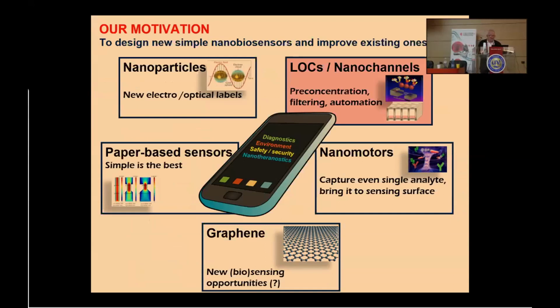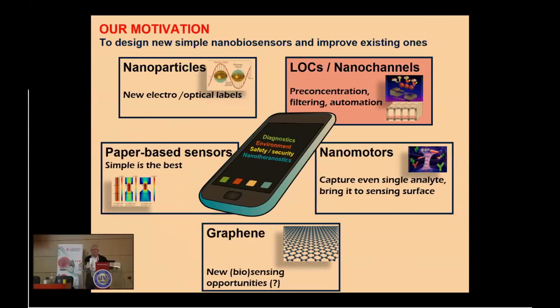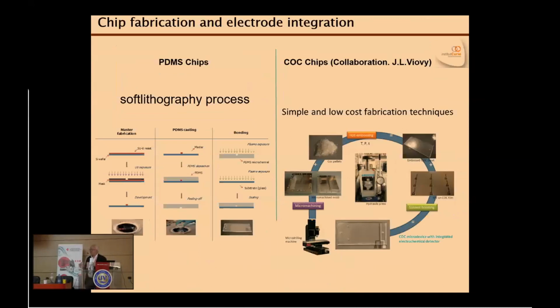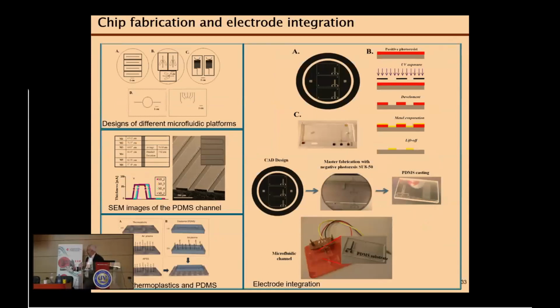So moving to microfluidics, as I said, sometimes life is not that easy, but with biosensors, you may have a lot of troubles if you are not able to pre-concentrate, if you are not able to remove the interference. So this is why we have a nice technology. We use soft lithography process and also thermoplastics. These are standard technologies used for building microchannels. I show you here, you can see it better. So we may produce channels with different shape, size, using different polymers.